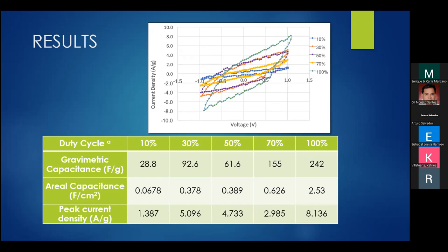from, if I'm not mistaken, 0.3 to 0.7 or 0.8. So from there we calculated the gravimetric capacitance in farad per gram and the areal capacitance in farad per square centimeter. From the tabulated results, you can already see that the film electrode synthesized at 100% duty cycle gave the highest gravimetric capacitance.